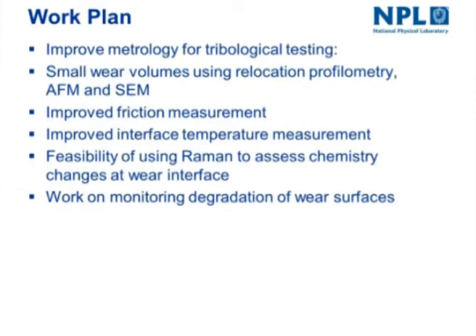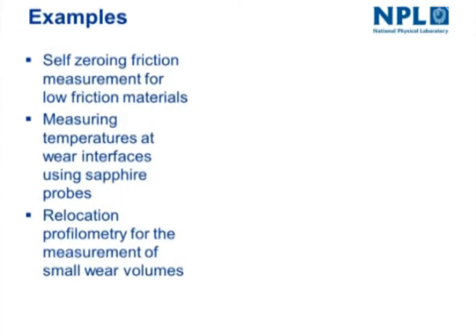The main purpose of this project is to improve metrology for tribological testing, to develop techniques for measuring small wear volumes, and this is related to acceleration of testing. If you can't accelerate, then you have to measure small wear volumes, and the main technique we're using is relocation profilometry, AFM and SEM, improved friction measurement, improved interface temperature measurement, feasibility of using Raman to assess chemical changes at the wear interface, and work on monitoring degradation of wear surfaces. So examples of what we've done here: we've now developed a self-zeroing friction measurement system for low friction materials. Drift of friction measurement is an issue that we're hopefully getting over. Measurement of temperatures at wear surfaces, and we are doing that at the wear surface itself using sapphire probes. And as I said, relocation profilometry for the measurement of small wear volumes.